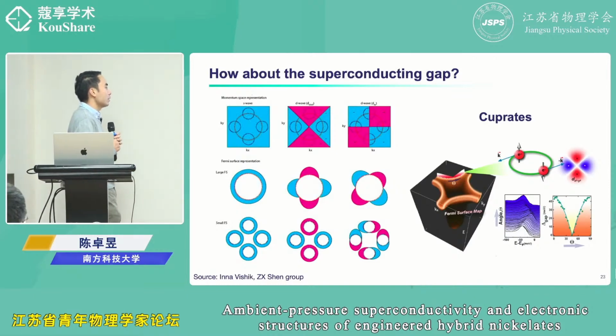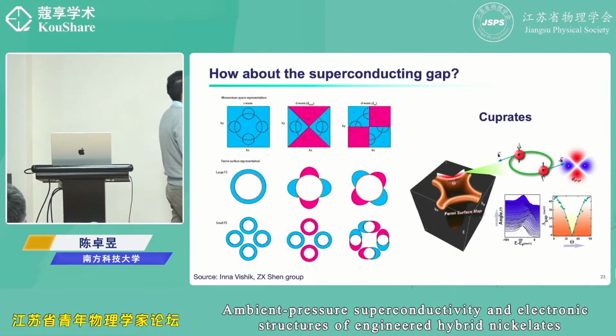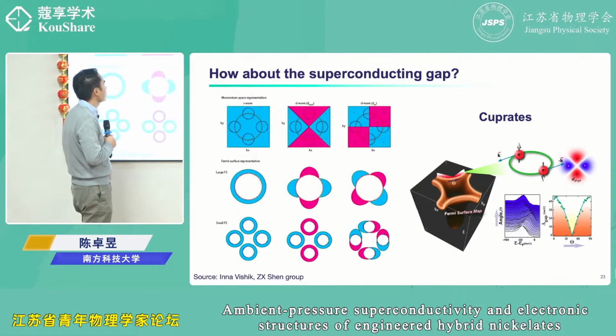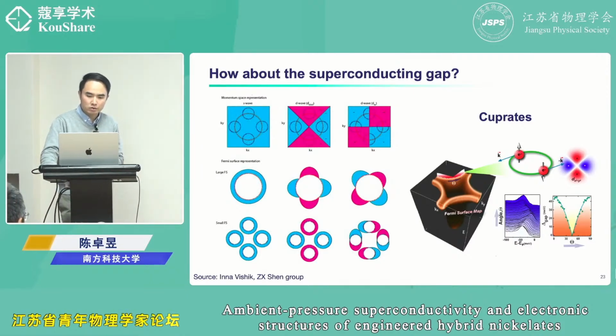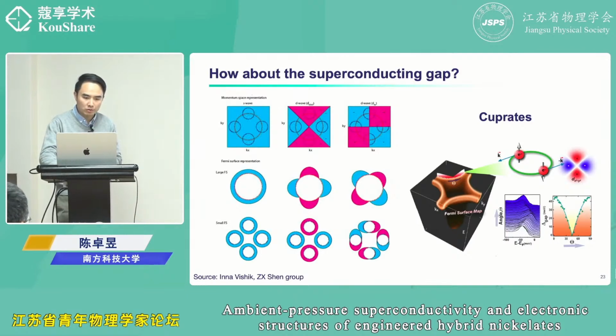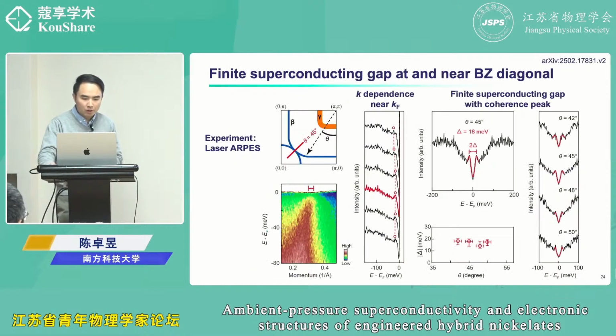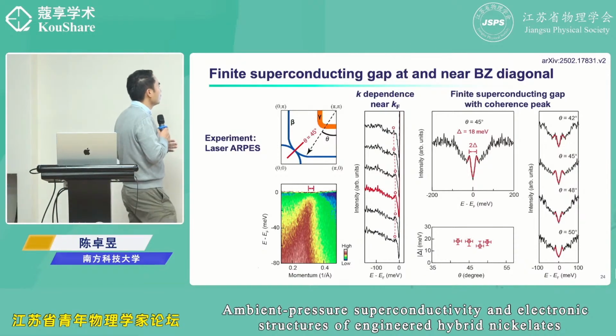So in the cuprate case, all ARPES measurements are the same as this scenario. ARPES in cuprates is very strong evidence for this d-wave superconducting gap. For nickelates, the first thing to check is this 45 degree. At 45 degrees, we see quite a clear gap with the superconducting coherence peak. So it looks very similar to a superconducting gap.